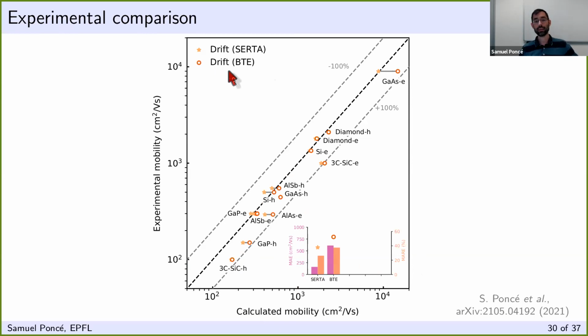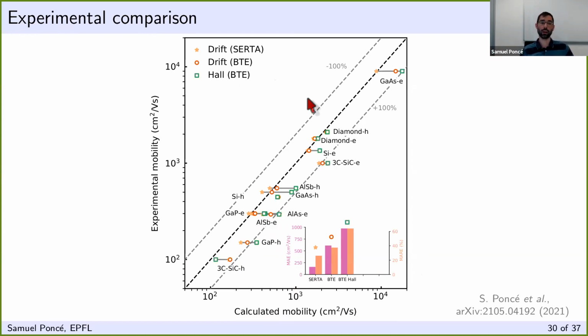Now, if we instead solve the iterative solution, systematically we will increase the value, and so the mobility will be overestimating experiment a bit. Now, if we also include the Hall factor, then we have this Hall mobility, which is what we should compare, because, I haven't said it, but most of the experiments I'm comparing with in this plot are Hall mobility experiments, simply because drift mobility data don't exist for those materials. And you can see that in those cases, we quite strongly overestimate the experiment.